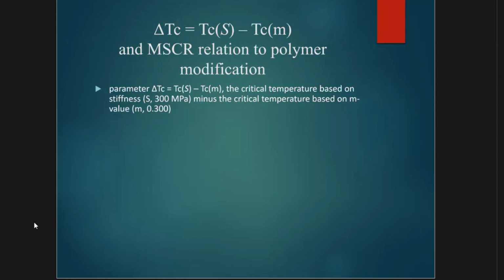I'm going to make the first caveat here. I talk about asphalt being ductile going to brittle. We talk about modification. There was no modification, and there was modification with SBS, if you like. That was the traditional modifier. There are other modifiers and so forth. All the modifier does is increase the modulus, stiffen the material, right? And if you're not careful, some of them may even change the bottom temperature of the asphalt.